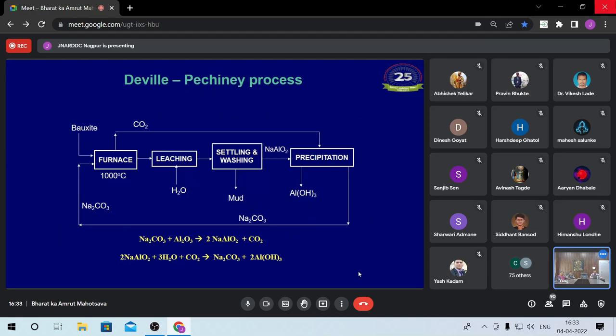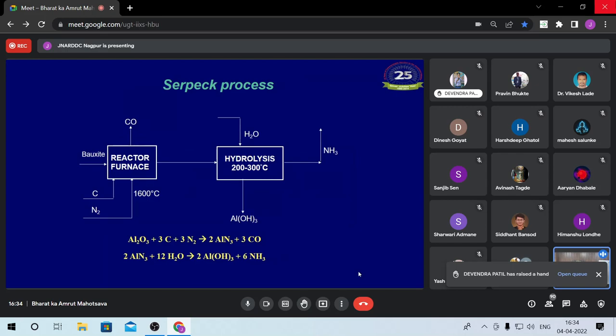This was on the basis of using sodium carbonate or soda ash, and again the bauxite was heated to a temperature of 1000 degrees with evolution of carbon dioxide and formation of solid sodium aluminate. This was leached with water to get the sodium aluminate solution, and then carbon dioxide was bubbled to precipitate out the alumina trihydrate, and this alumina trihydrate was then processed, calcined, and then sent to the smelters for electrolysis. Then there was the Serpek process.